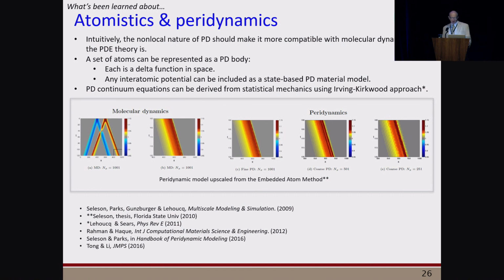Because peridynamics is a non-local theory, there is the possibility of using it more effectively than the standard theory as a way to coarse grain atomistics and to implement atomistic to continuum coupling. And there have been some studies of that, but it seems to me there's a lot more that could be done in the future. Interestingly, you can go directly from statistical mechanics to a peridynamic continuum model, and that result was explored by Lehoucq and Sears in about 2010.